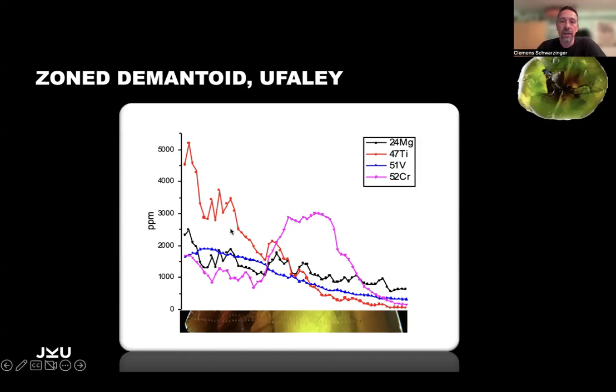And when the titanium goes down, then we have here an increase of chromium. So the intense green zone, the vibrant green, is due to the chromium and not titanium. Now, if you understand this